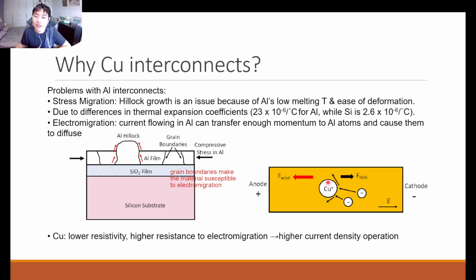This will cause a movement, or you can call it a diffusion, basically a motion of these metal atoms in a certain direction, and we call this electromigration because it involves the migration of the metal atoms under the influence of the electric current. So what drives the replacement of aluminum with copper is the fact that copper has a lower resistivity. That in itself is a good thing because it reduces the delay in the transfer of signals in your circuit. It also reduces the amount of loss of electrical energy to heat. In addition, very importantly, it also has a higher resistance to electromigration and stress migration. Specifically, its higher resistance to electromigration means that we can operate the device at higher current densities while still keeping electromigration to a much lower level compared to the use of aluminum interconnects.